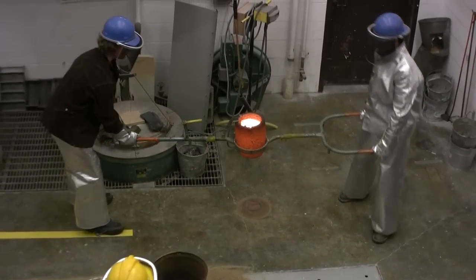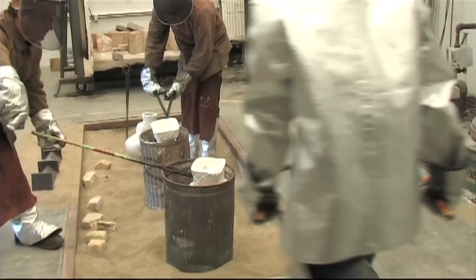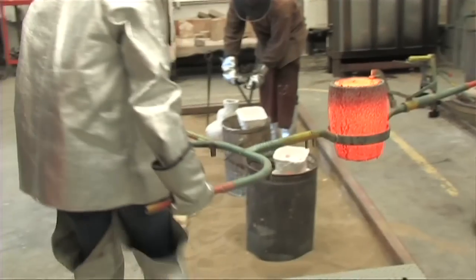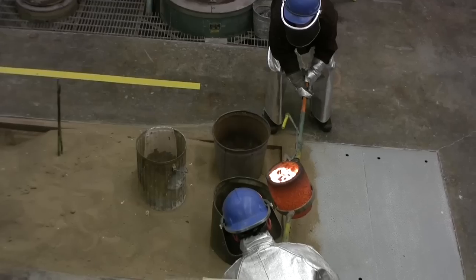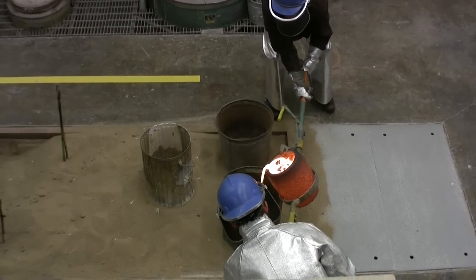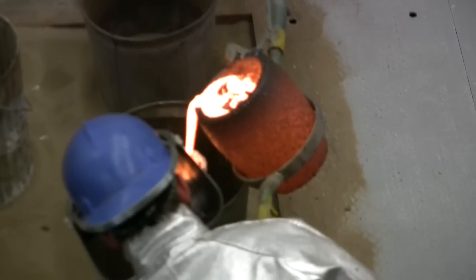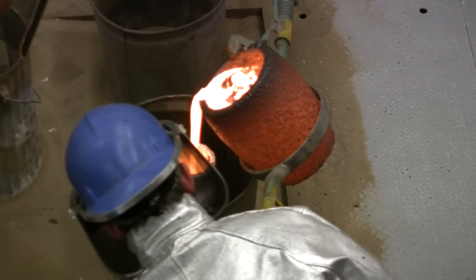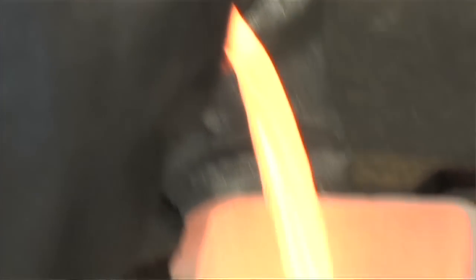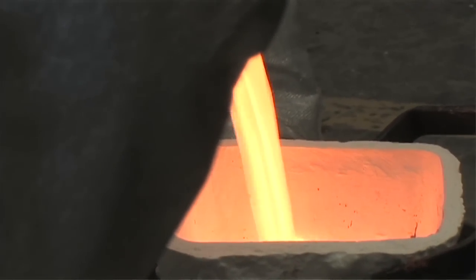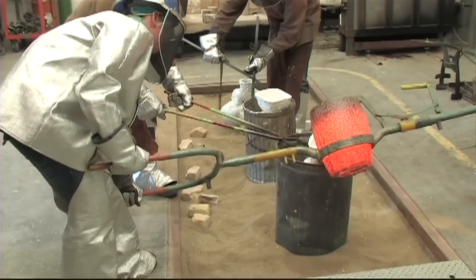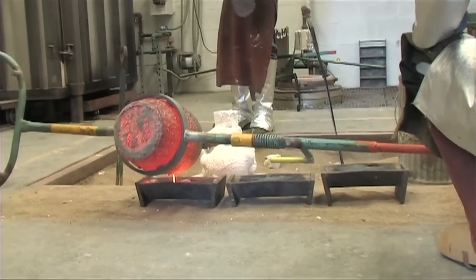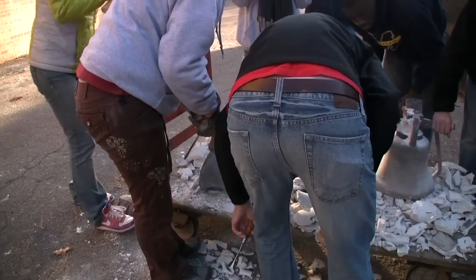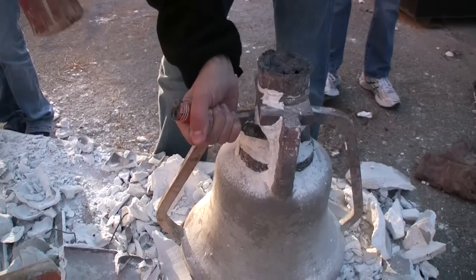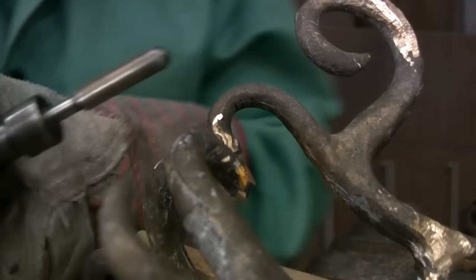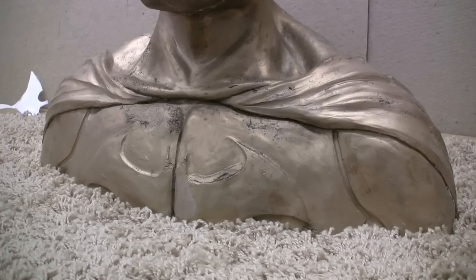Somebody's moving out of the kiln, and these guys in spacesuits are pulling a pot of 2,000 plus degree metal. You're dealing with extreme materials here. I mean, not to get too crazy, but it could melt your face off. And you certainly don't want to melt your face off. And inside that ceramic mold is a thousands degree hot replica of your original sculpture, which in about 12 hours or so, you can break out of that mold. And inside of it is your statue, your sculpture in bronze. And that's how you make a bronze sculpture.